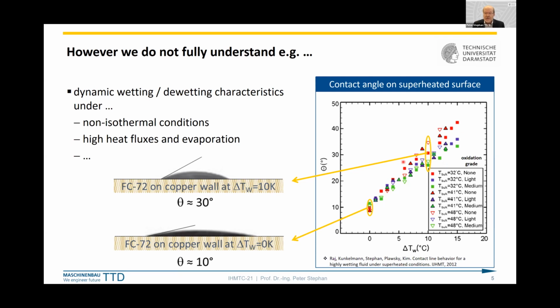What we also see in this plot: at isothermal conditions, it's basically independent of the oxidation grade of the surface. However, at higher temperatures, the oxidation grade, whether non-oxidated, slightly oxidated, or medium oxidated, also changes and has an influence on the contact angle. So under non-isothermal conditions, the situation is quite different than under isothermal conditions, where the majority of correlations, for example for contact angles, are developed.